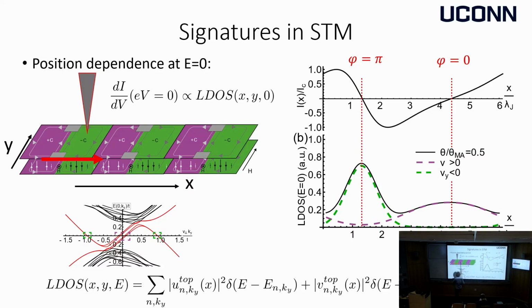So it's really like in this picture. The states along this vortex core go in one direction, but the states along that vortex core go in the opposite direction. And you can basically induce this by magnetic field. You don't need any contacts. And then you can come, for example, with an STM probe and see that the inside of this region is gapped, but the density of states at the vortex cores contains those gapless states, and it's precisely those that are also carrying the chiral currents.